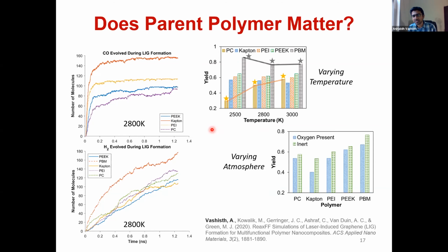Another very interesting observation that we saw was that the yield decreases when the simulated LIG conversion is carried out in the presence of oxygen. And that's kind of intuitive because the oxygen is kind of aiding in the oxidation of the polymer as well. But if you look carefully here, Kapton sees a much higher drop in yield as compared to PEEK or let's say PEI, which is also a very interesting observation.